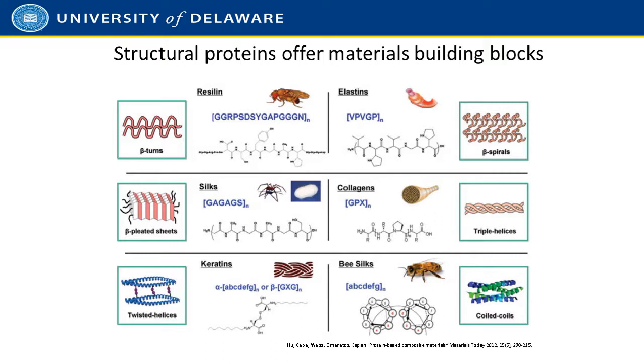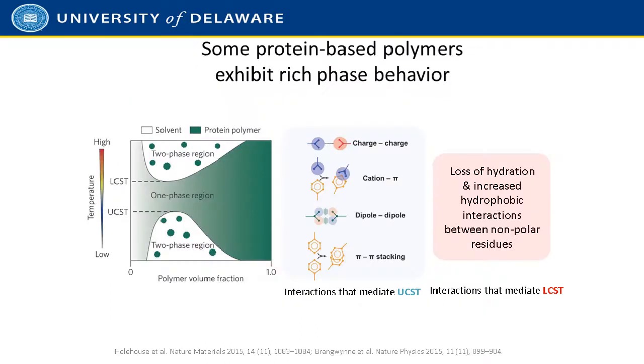And as you progress through this set of structural materials, you can see higher orders of structural control as you would go through the elastins and then the silks. And then once one considers the collagens, the keratins, and the bee silks, individual chains will then hierarchically assemble into larger order structures that then can carry significant load. So we've looked a lot at resilin, elastin, and collagens, and I'll tell you a little bit more about why.